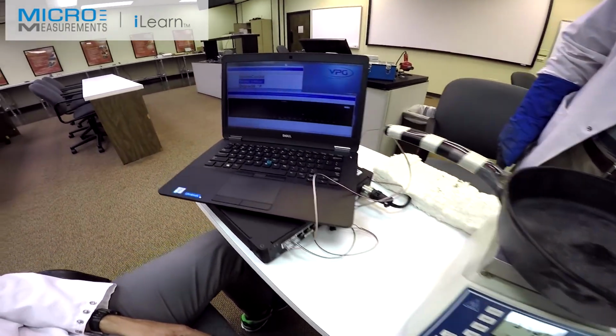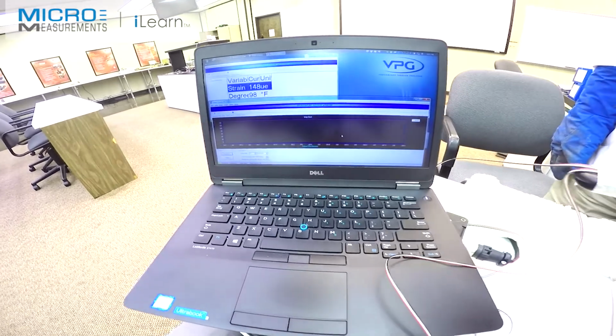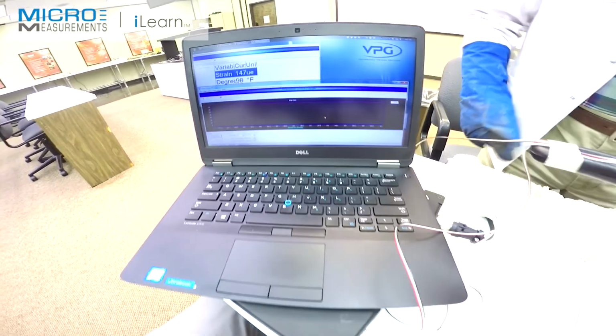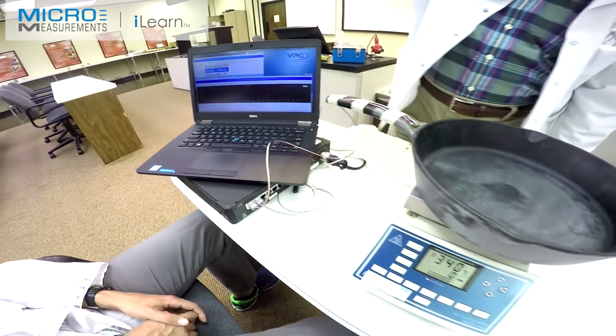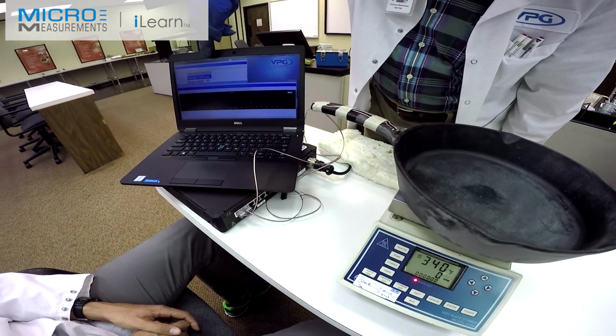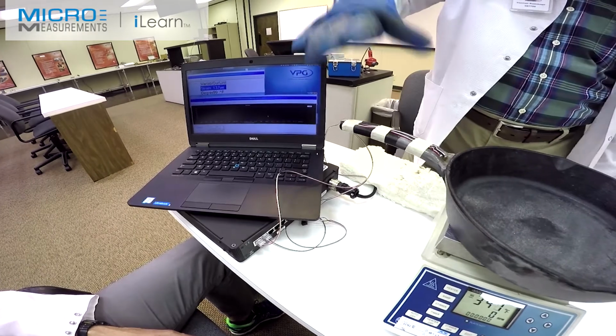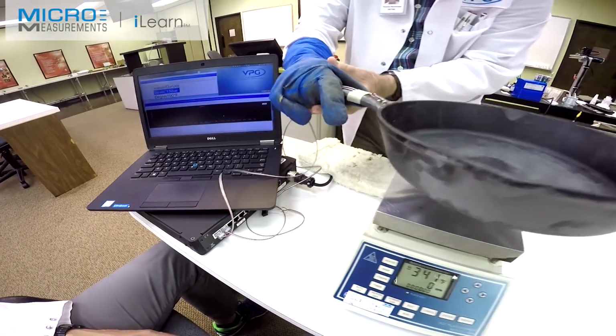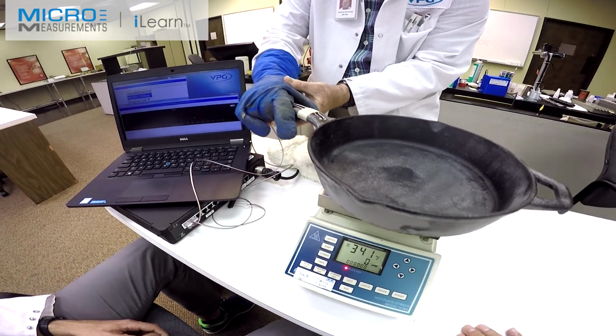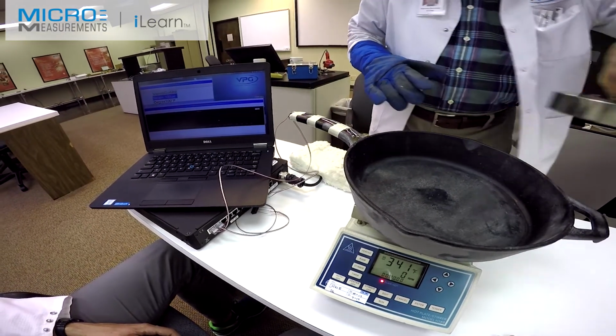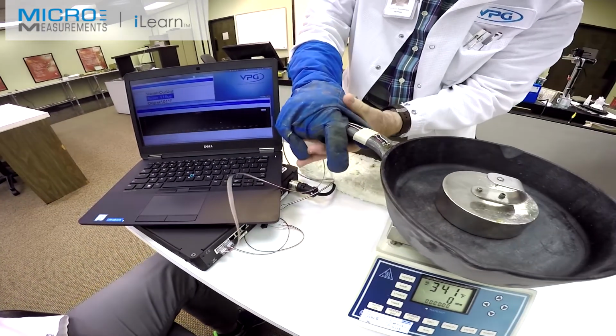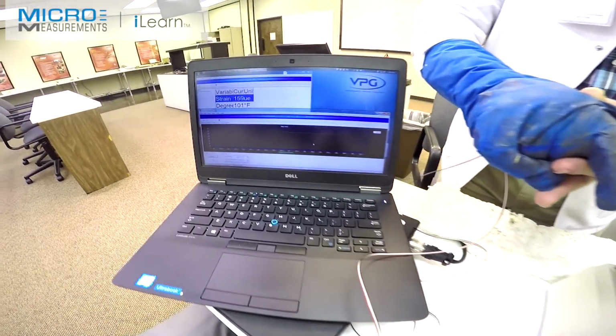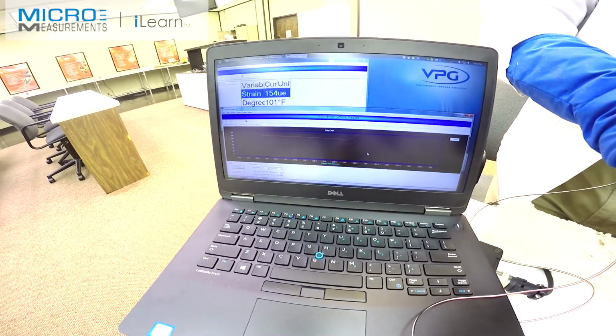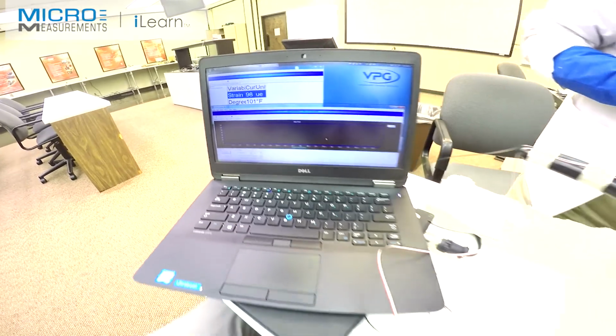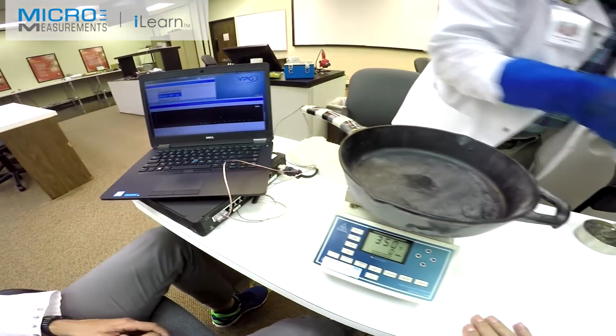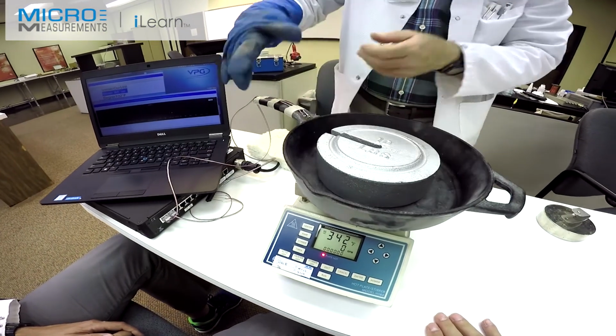Now the temperature of our handle has gotten up to about 100 degrees Fahrenheit, 98 among friends. Now let's see if the strain change is going to be different. Now notice we have a thermal output of nominally 140 microstrain. So we'll take that and we'll add this strain to it. We'll go to the 4 pound weight and compare that. And then the 10 pound weight, that big old piece of steak that Matt wanted to have.